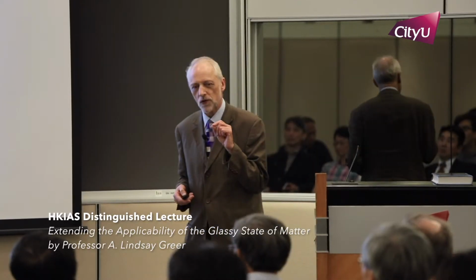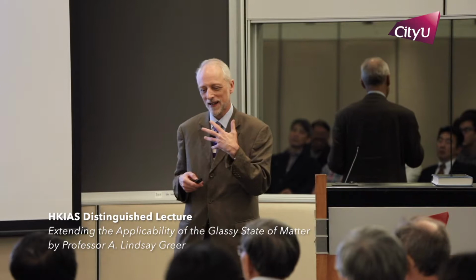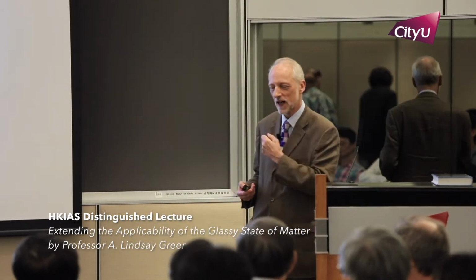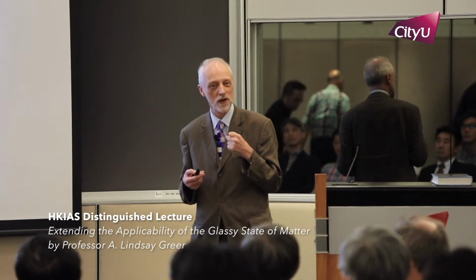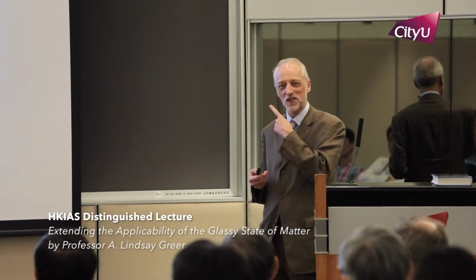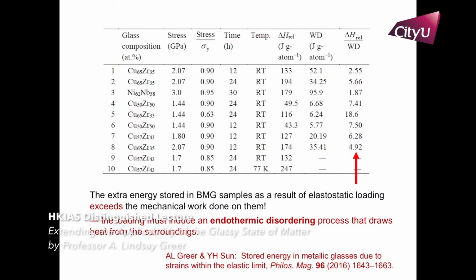In the business of storing energy in these systems as a result of deformation, I have talked in terms of percentages. So I have said, for example, in classic crystalline metal rolling, a few percent of your work done is stored as energy in the changed structure of the material. And in the metallic glasses, we were getting rather higher stored energies, but it's some percentage of the work done. This turns out to be exceedingly odd, because we can work out the work done and compare it with the stored energy.